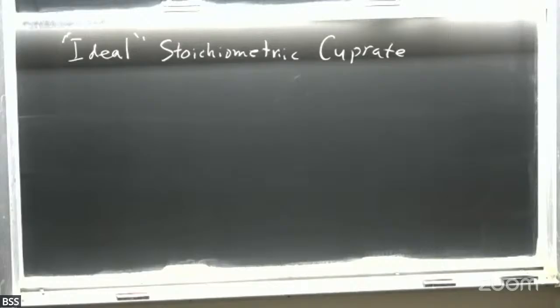They're solid state solutions, which means that there is intrinsic randomness in them. So even if they are perfect, what perfect means is that the distribution of strontiums on the lanthanum sites is statistically uniform. It does not mean that it's uniform. And so intrinsic disorder, and for reasons that I'm going to get to, I think that some fraction of the things that are perplexing about the phase diagram are actually reflections of the presence of this disorder. Okay, there are in principle experiments without varying doping, without varying geometry. But as Senthil said, I'm a theorist, so you can't stop me from imagining it. So that's what I'm going to do for now.